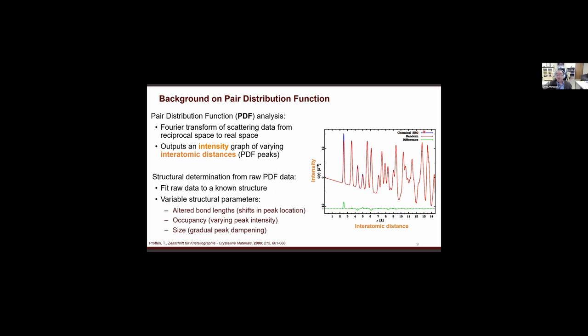For example, this blue one is from a chemical short range order, and it's a model to fit this, and this is the remaining difference. The smaller this difference, the better the fit. Structure determination from the raw PDF data is normally difficult; solving an unknown structure is possible, but it's not that common. Normally, it's fitting raw data to a known structure.